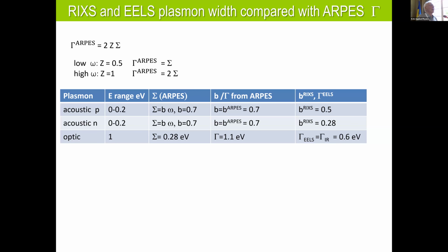What's your feeling? I have looked, for example, through the optical data. And there's a large scattering in the memory function or in the scattering rates, but in total, at least in the average, there's not so much deviation. And the same holds for the ARPES data. For example, the saturation occurs at 0.4 eV and ours was 0.9 eV also.